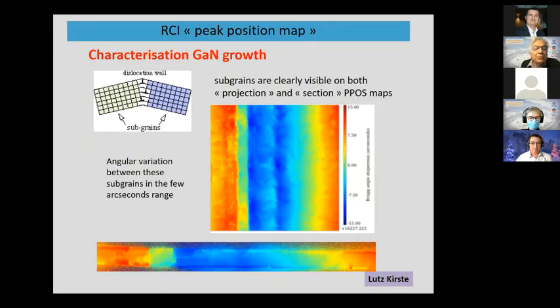For instance, when you have subgrain boundaries, which are regions of the crystal which are slightly rotated one with respect to the other, with a dislocation wall, the peak position map shows you here and there that you have regions where you have different orientations of the crystal. And you can see, if you look at the scale, that the angular variation between the different subgrains, which are clearly seen in this peak position map, is only in the few arcsecond range. And the same for the section topography. This is a very sensitive technique where you can see very clearly variations of orientations in the arcsecond range.